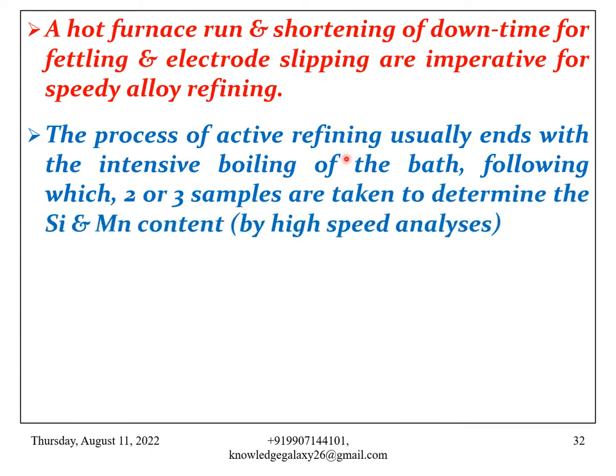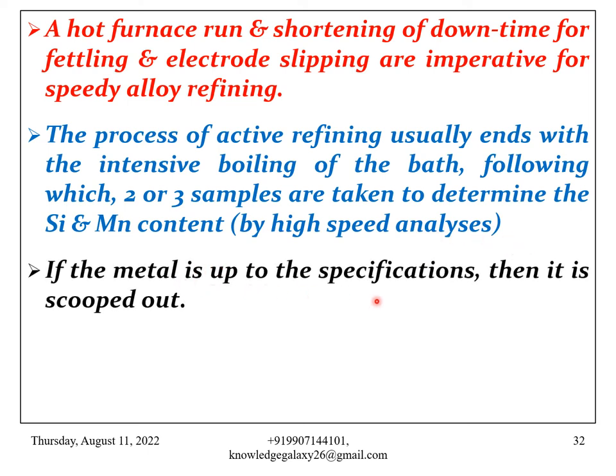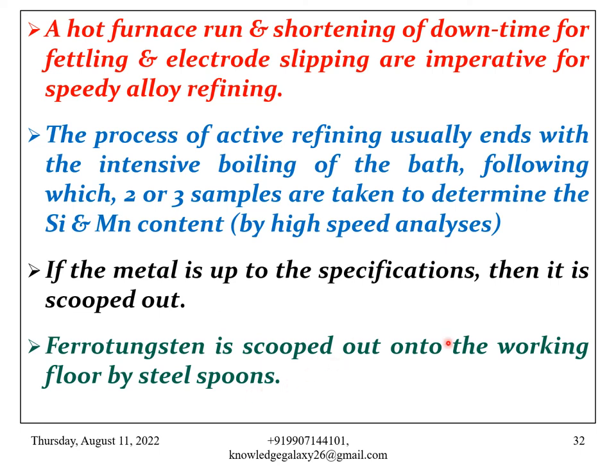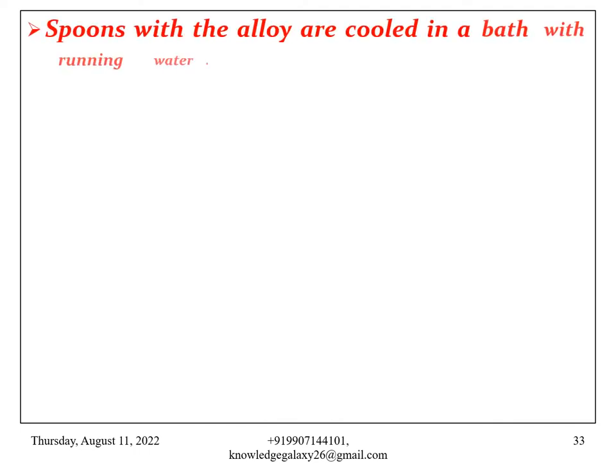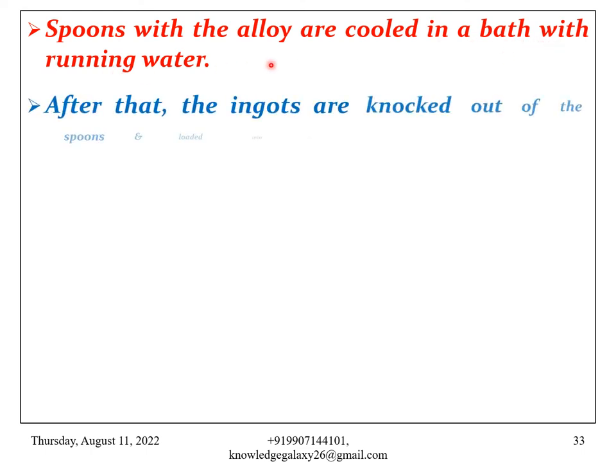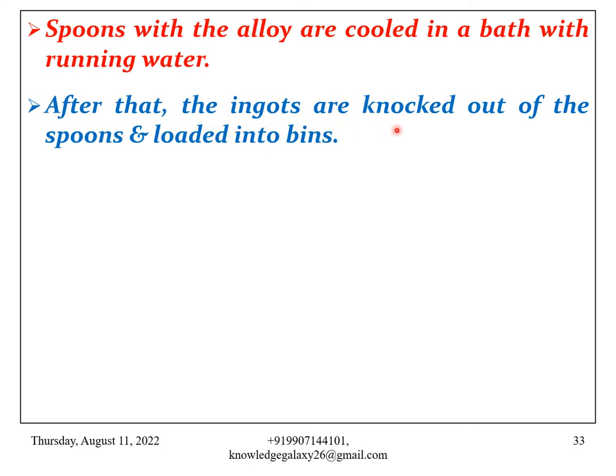The process of active refining usually ends with the intensive boiling of the bath, following which two or three samples are taken to determine the silicon and manganese content, that is by high speed analysis. If the metal is up to the specifications, then it is scooped out. Ferrotungsten is scooped out onto the working floor by steel spoons. Spoons with the alloy are cooled in a bath with running water. After that, the ingots are knocked out of the spoons and loaded into bins.